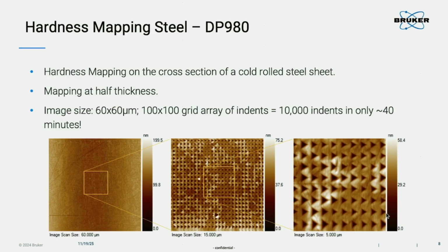So this is an example, just for the 1 million indents. No, this is a 10,000 indent array, so 100 by 100 indentations. If we look at this, if you want to do perfect properties mapping, you want to make sure all the indentation marks are separated, and you have to do some preparatory work. Firstly, you want to know the indent. You can see this is a softer indent, this is a softer material, and this is a harder material. With the same force, the indentation mark is different.